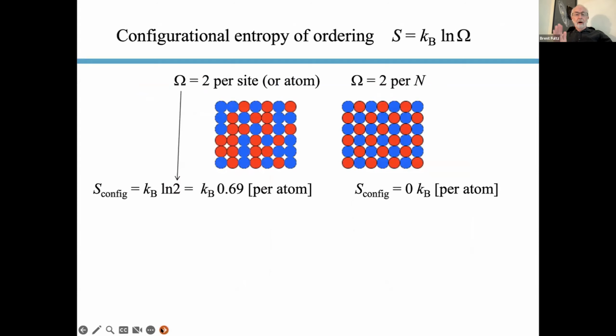Okay, you all know about the configurational entropy, I think. Here's an equiatomic red and blue alloy. We put a blue atom on the upper left here, and the next ones go down randomly with two possibilities, irrespective of what their neighbors are. So that's logarithm of 2. That's our W or our omega, and that's per atom. On the right, we could have a blue or red here, and the rest are all defined. Once we put down the blue, then we know its neighbors, and that is basically 2 per Avogadro's number, which is 0. So that's sort of the range of configurational entropy. Log 2 is 0.69, and 0.69 kB per atom to 0 is about what we can expect.